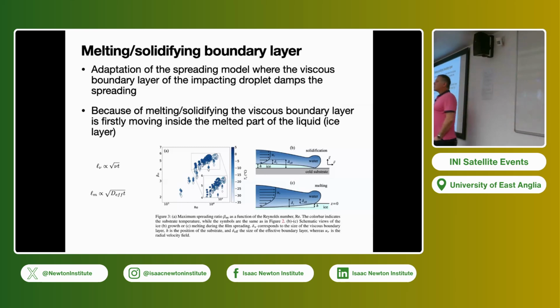If you remember, the viscous boundary layer grows as square root of t. We are lucky because, as you remember, the ice layer, to first approximation, also grows as square root of t. So we can consider a very simplified model where, instead of having only the viscous boundary layer, we have the viscous boundary layer plus the melting or solidifying layer. Now I just adapt my criterion: when the sum of my viscous boundary layer and my ice layer, or the difference between my viscous boundary layer and the melting layer, meets the free surface, it gives me a criterion for the maximum diameter.